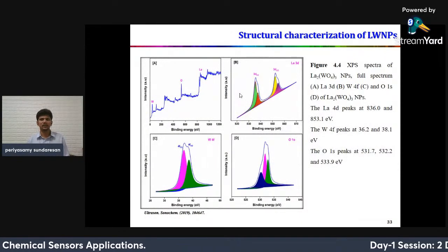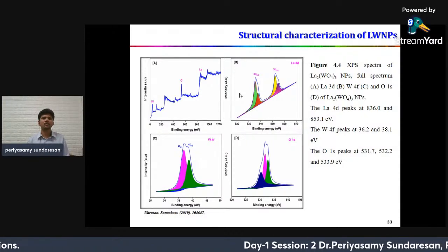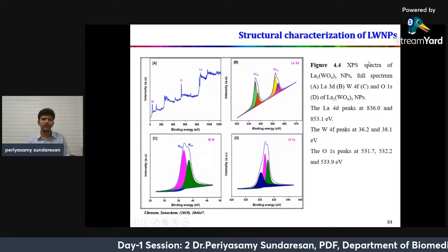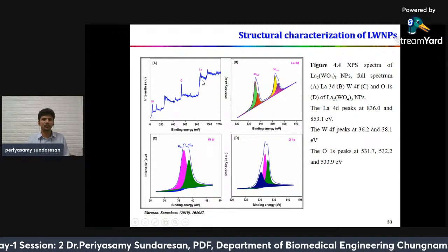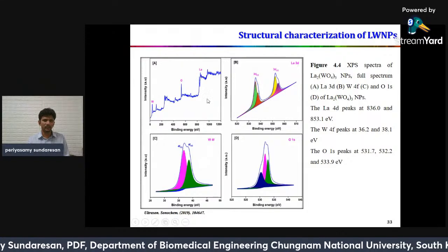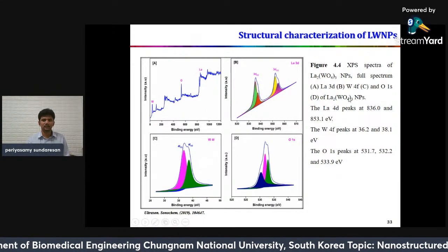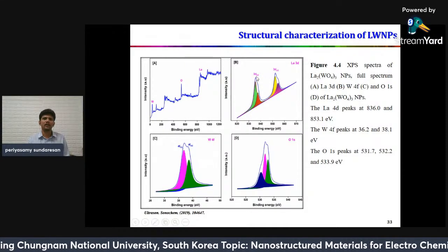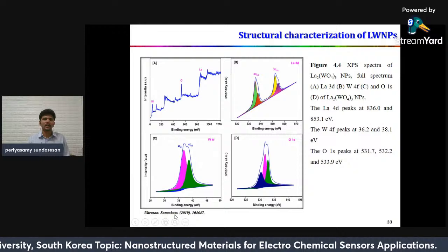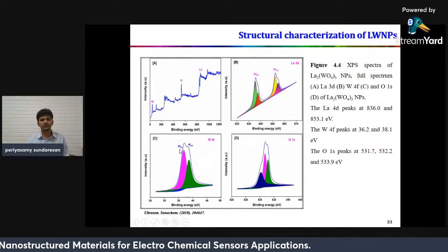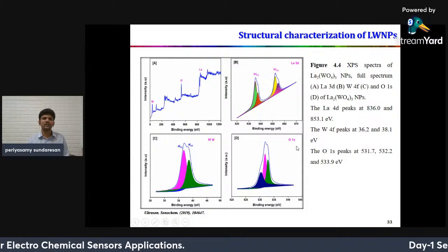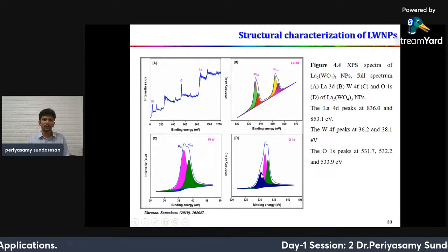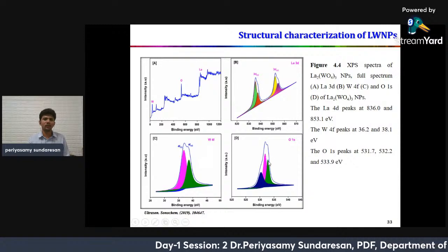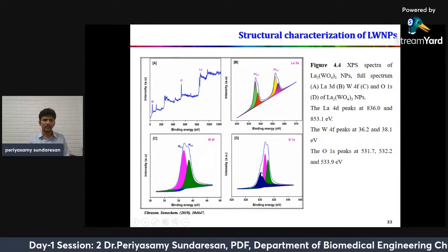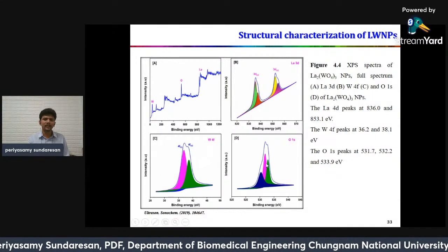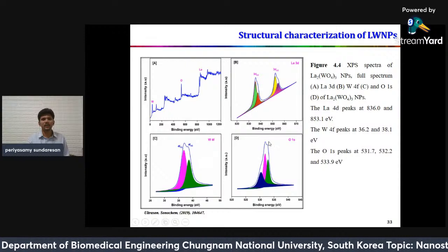The structural characterization of the lanthanum tungstate nanoparticles: the lanthanum is checked with XPS analysis. Here the lanthanum is deconvoluted into 3d 5/2 and 3d 3/2, and the tungsten 4f is deconvoluted into 4f 7/2 and 4f 5/2, and the oxygen is deconvoluted into 531.7, 532.2 and 533.9. It means the lanthanum tungstate is formed in this oxidation state without any other impurities.